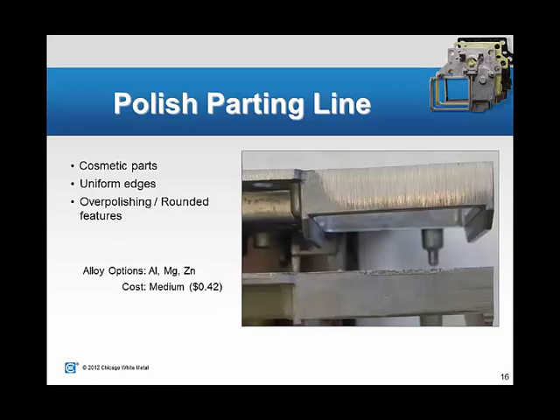The above image shows what happens when you remove that gate vestige, and once a powder or wet paint or another cosmetic finish gets applied to that, it looks fantastic. You could never tell that there was a gate or any other tooling remnant visible. Again, we would consider this for cosmetic parts. The only concern potentially to look out for is maybe over polishing and rounding some features. So if you need a nice straight edge all the way through, just something to consider that you don't want to over polish. Again, all three alloy types are suitable for this, at a 42-cent relative cost.